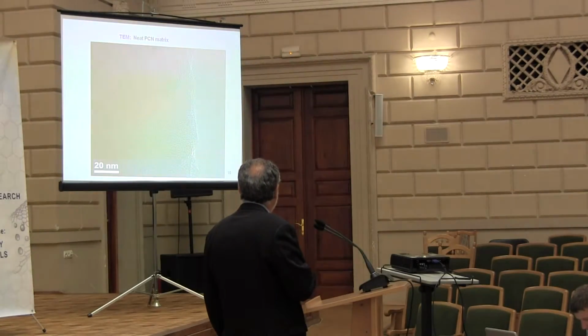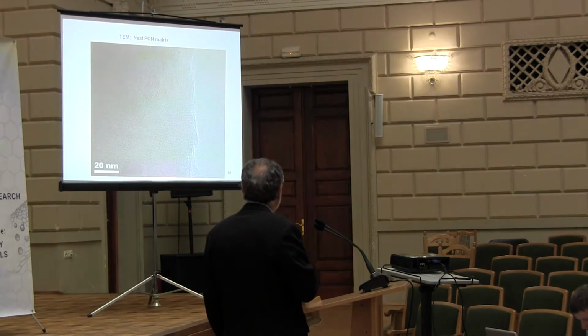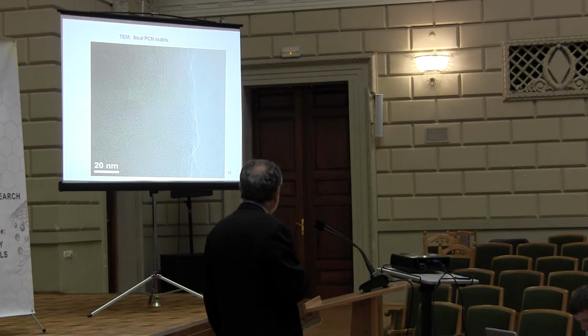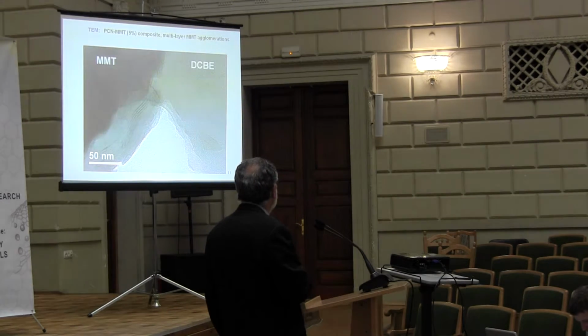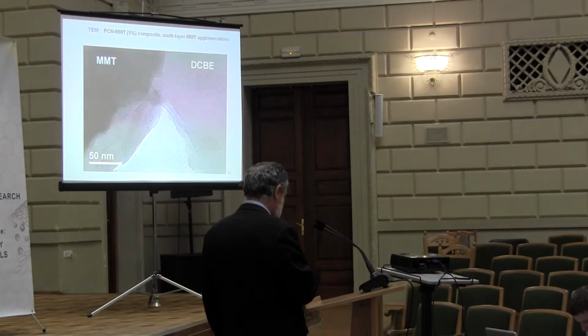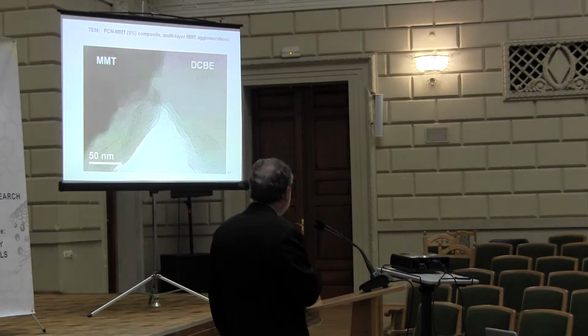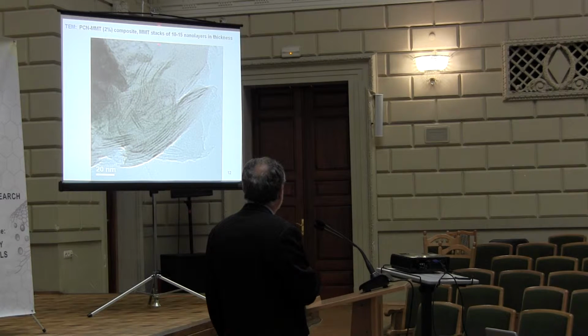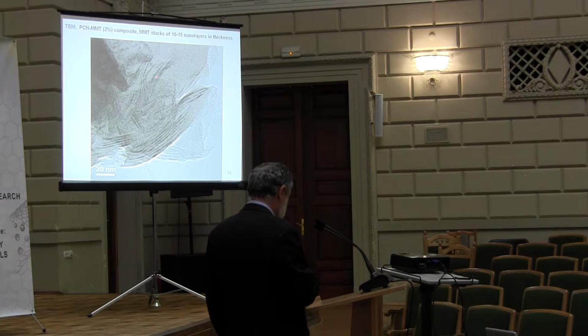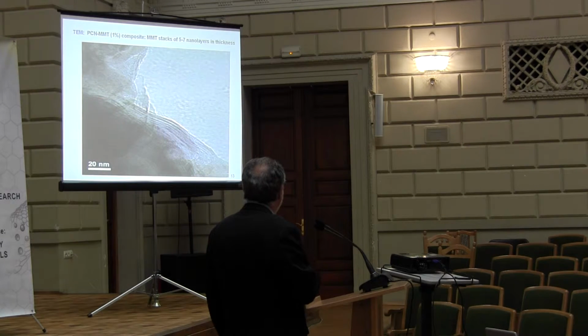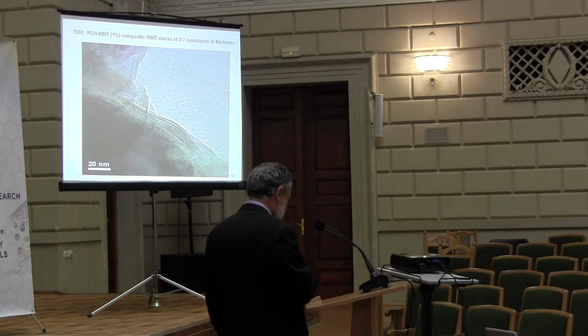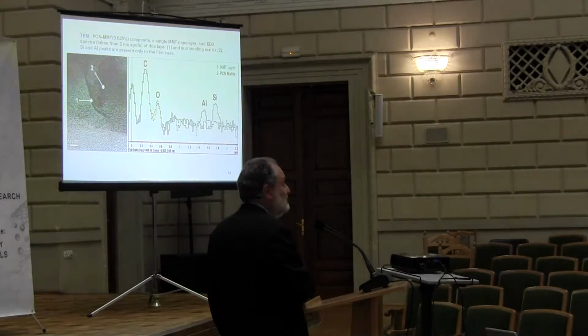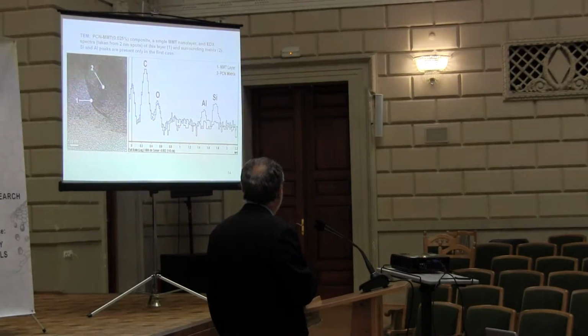And here we have the TEM photos for the net polysaccharide matrix. Then it is for 5% montmorillonite composite, which shows us the multi-layer montmorillonite aggregates in the polymer matrix. Then for 2%, we have stacks of 10-15 nanolayers in thickness. For 1%, we have 5-7 nanolayers in thickness. And for the best sample with 0.025% composite, we have a single montmorillonite nanolayer.